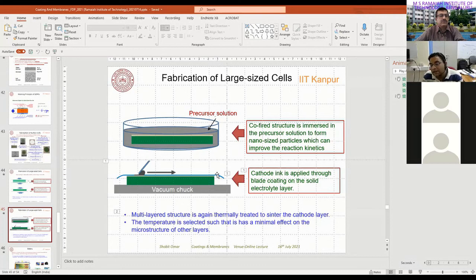Like in this particular case, gadolinium nitrate and cerium nitrate. That solution is poured over it, and then you dry this whole sample in vacuum, so that the solution covers the scaffold that you have formed. In that way you get small nano-sized particles on your structure. Of course, you have to calcine it, otherwise it will remain like gadolinium oxide or cerium oxide. You have to calcine it for the reaction to occur to form gadolinium-doped ceria.